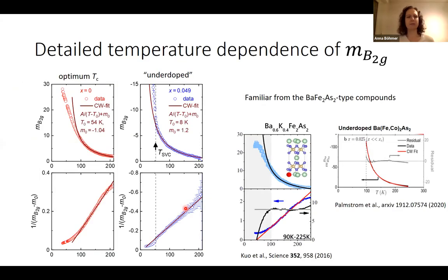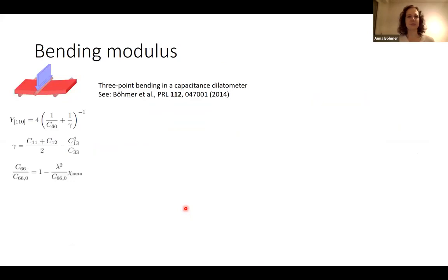But while we still don't really know about this prefactor, we thought we might try a different probe, the bending modulus, where this resistance prefactor does not enter. What we have here is the same equation that Matthias just used. The nematic susceptibility influences the elastic shear modulus. And with this coupling constant, this combination is dimensionless, and it has to be 1 at the transition. At the nematic transition, the shear modulus vanishes. So we have some handle on the units here.